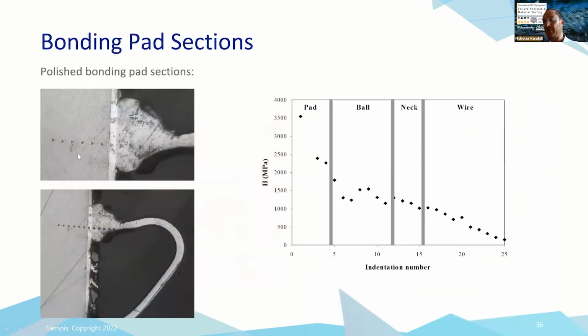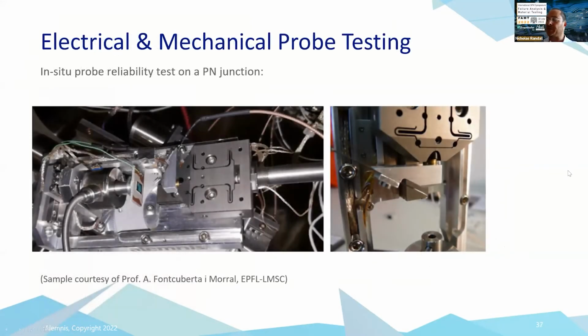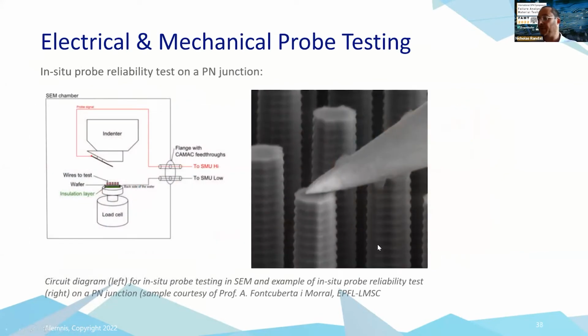We can also map through sections of bonds. So this is looking at the coating and the bond wire. We can also look at different areas of the bond wire. And this is simulating the actual probe testing by mounting a probe on the Alemnis system and then being able to apply that probe. For example, here we're doing it on PN junctions and we're functionalizing the indenter probe tip with a closed circuit. So we can also look at the electrical properties and the load at which connection is made.